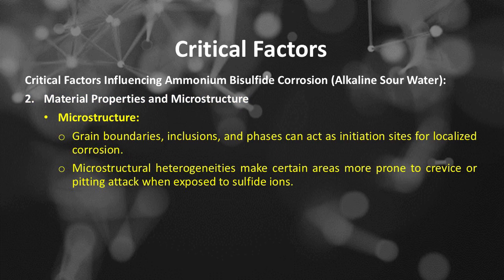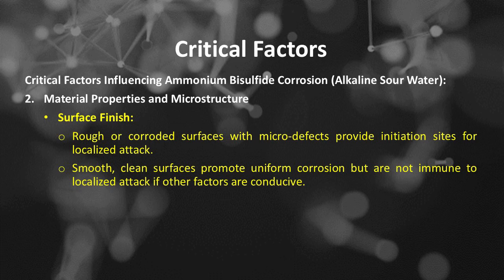The second is microstructure. Grain boundaries, inclusions, and phases can act as initiation sites for localized corrosion. Microstructural heterogeneities make certain areas more prone to crevice or pitting attack when exposed to sulfide ions. The third is surface finish. Rough or corroded surfaces with microdefects provide initiation sites for localized attack. Smooth, clean surfaces promote uniform corrosion but are not immune to localized attack if other factors are conducive.